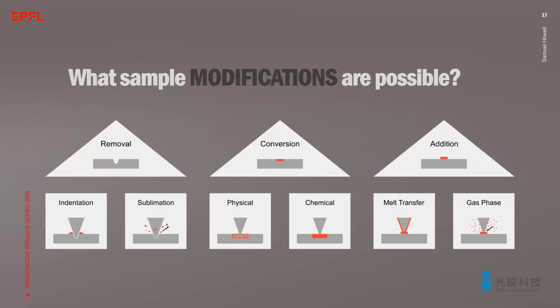With the materials that have been researched in the literature, we found there are 3 types of sample modifications: removal, conversion, and addition. Each modification includes different processes such as indentation, sublimation for removal, physical and chemical conversion of the material, or addition via melt transfer or from the gas phase. And we separated the modifications in these 3 different categories because there are different challenges in terms of the fabrication related to each of these groups.